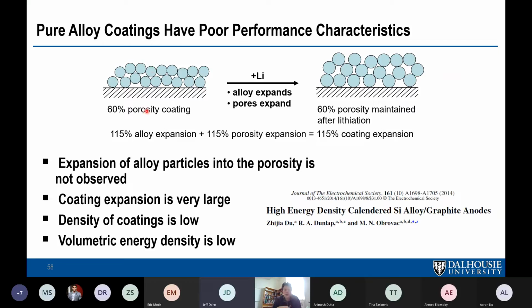of porosity will occur. And so basically what happens is all these particles expand at the same time, and the pores in between them expand too. It's just like taking this thing with a mouse and expanding the whole thing, and you get something that looks like this. That's still 60% porosity. And so after all your work in making something that can store a lot more lithium, you've got mostly empty space in your coating, and your energy density will be less than graphite. And that's why you have to add a graphite, so you can calender these things and get the porosity down.